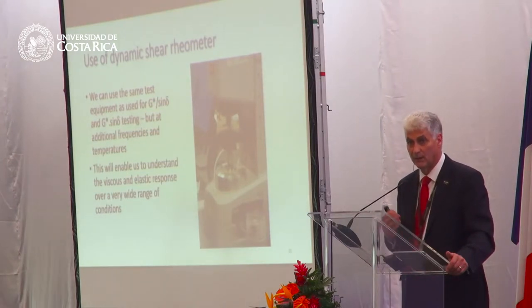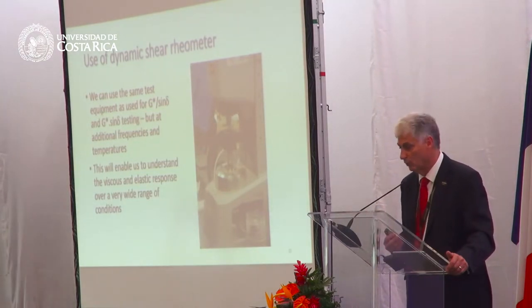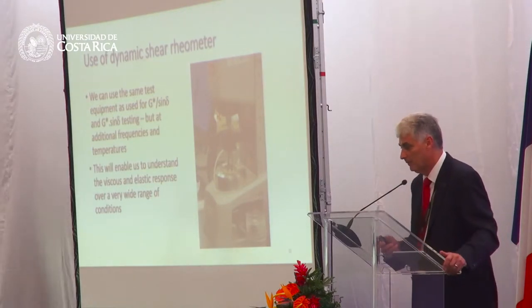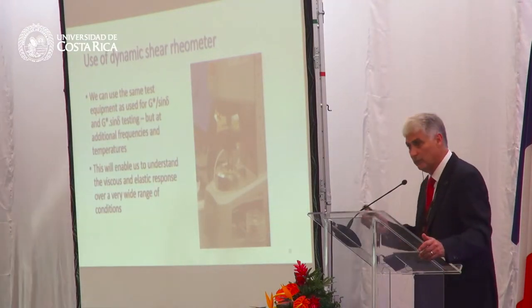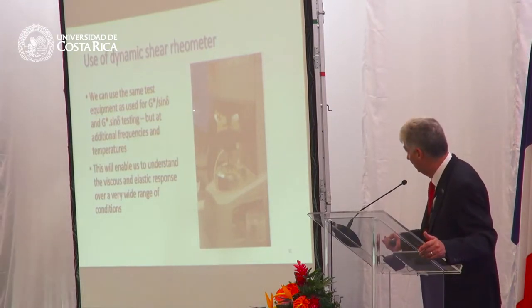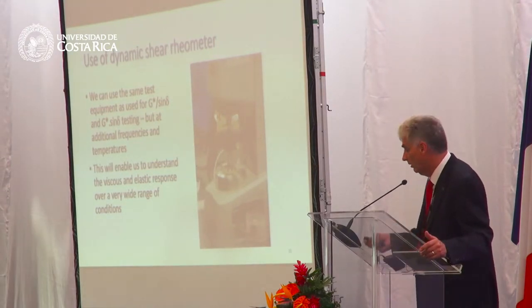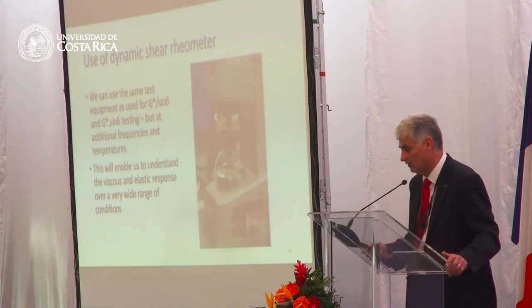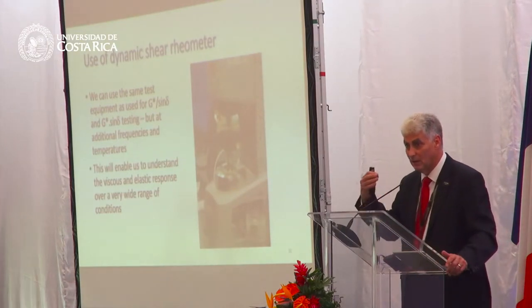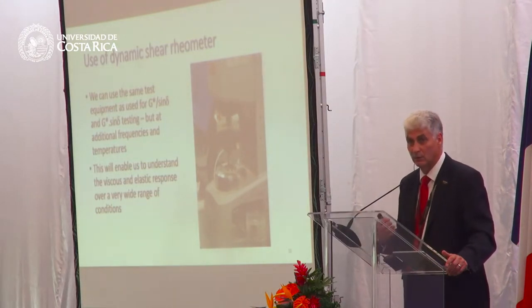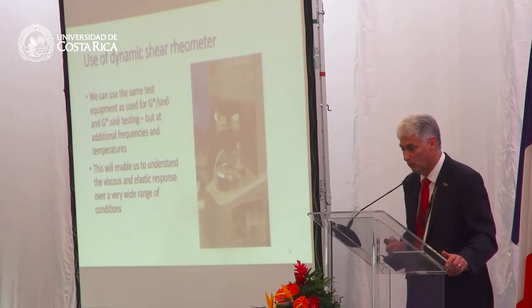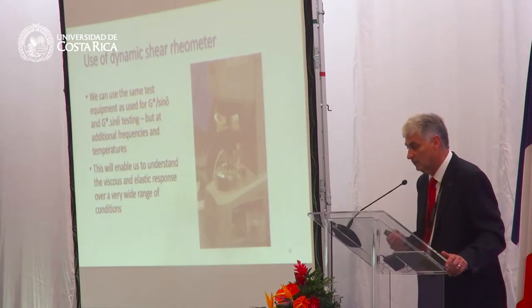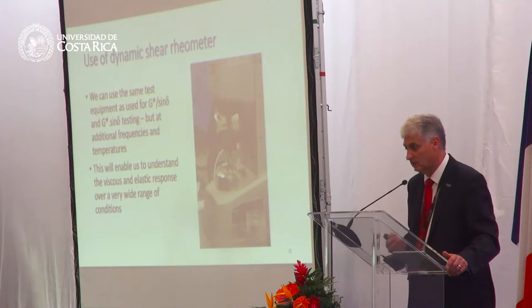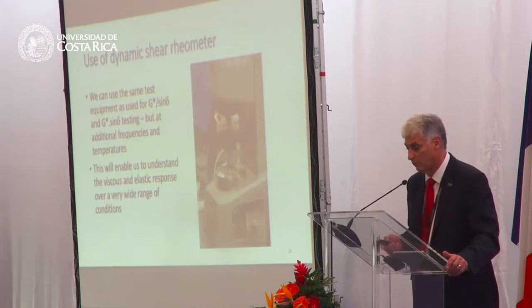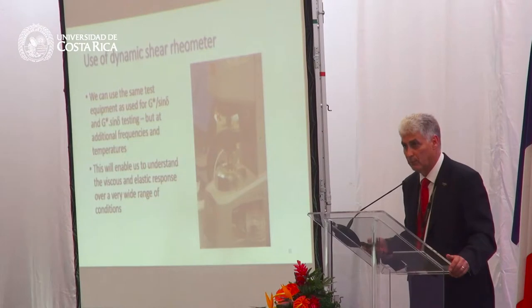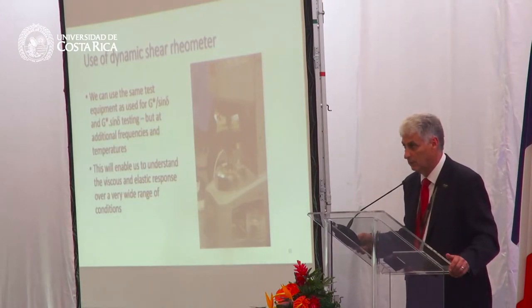Modern tools today, we have things like dynamic shear rheometers, bending beam rheometers. We saw several of these in the lab here. But we can get better information today by measurements of things like the complex modulus, G star times sine delta, G star divided by sine delta. But we can also do the testing at additional temperatures and frequencies. So we can produce things like master curves, which we saw a few minutes ago for the mixture work. And this enables us to understand the viscous and the elastic response over a wide range of conditions. So having that information is extremely useful today for the design of these binders.